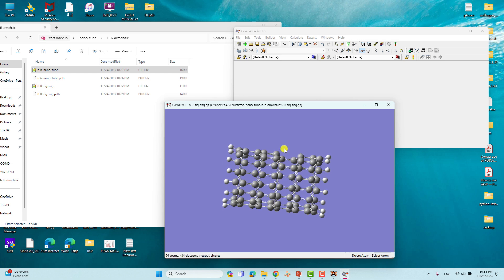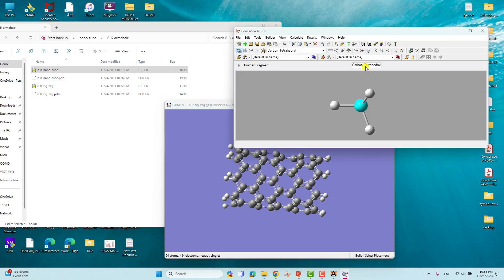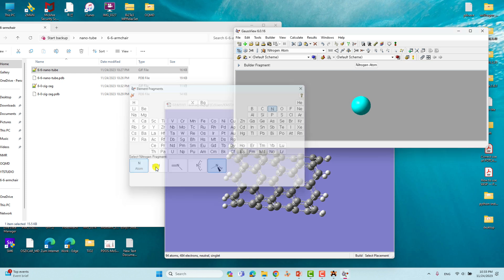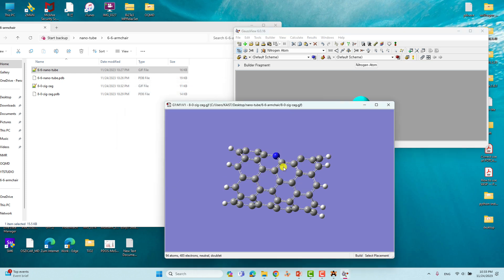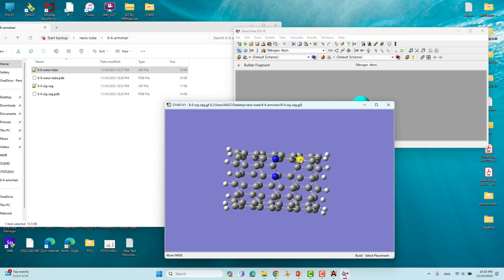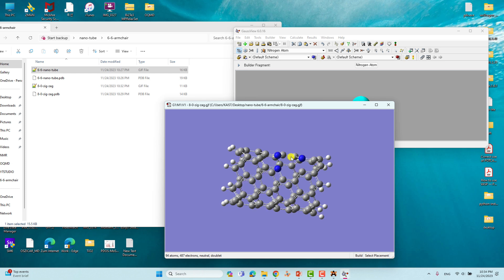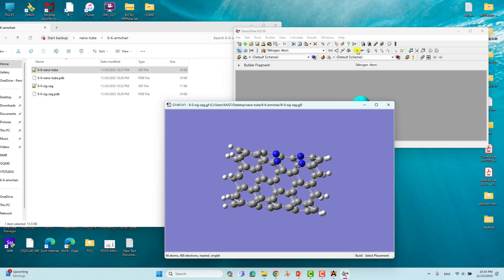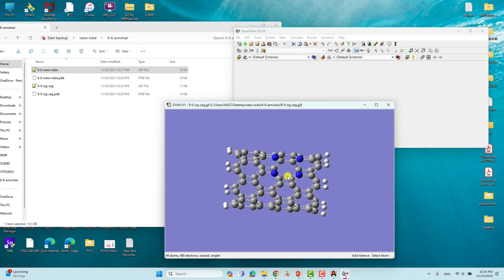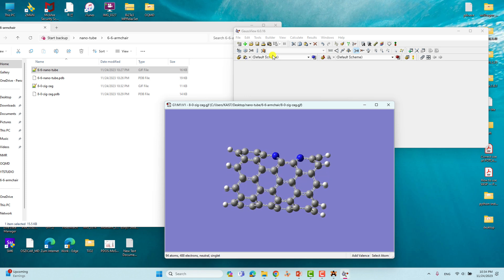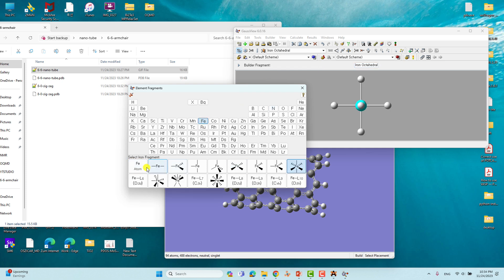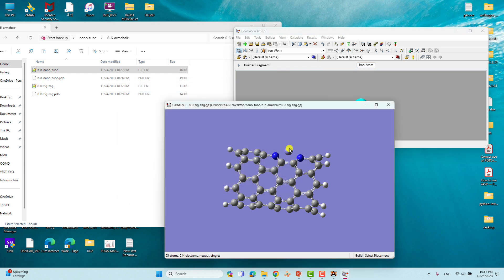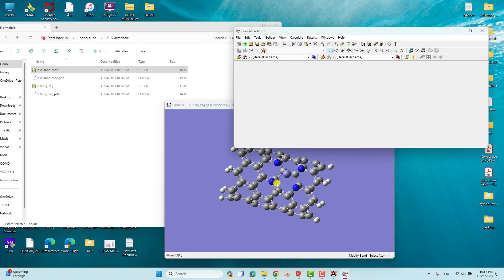Now add nitrogen atoms around the vacancy — add one, two, three, four nitrogen atoms surrounding it. Then add one metal atom inside that vacancy site. I'll add an iron atom and place it in the center of the vacancy, then maintain the bonding connections.